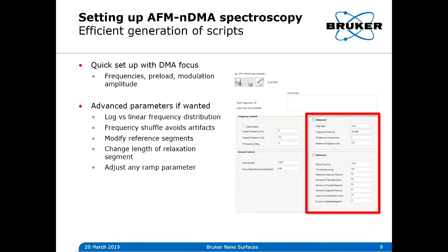This is similar to the DMA parameters that you'd have if you were working with a bulk DMA machine. However, if you work with atomic force microscopy, you may want to be able to adjust some other parameters. For example, exactly how you want to distribute your frequencies in the script, whether you want to shuffle them, how many reference segments you'd like, how much relaxation you'd like, how big of an approach you need, things like that. So all kinds of ramp parameters. So we do have advanced parameters if you need them. They can be adjusted in the ramp script generator. And once you've generated the ramp script, you can also load it into the general ramp scripting interface and use that to modify it. That gives you more flexibility, but it is, as I mentioned, a bit tedious when you start working with long scripts.